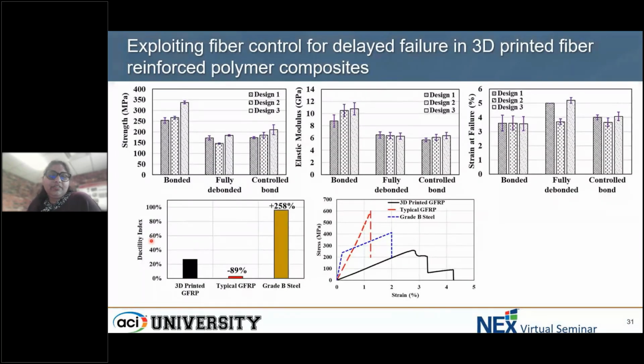Again, strength, modulus, and strain at failures, you will see that the bonded will be at the highest strength in terms of design 1 and design 2. But the design 3, you have a fully debonded one in terms of strain, that is higher strain at failures for fully debonded. And that controlled bond or thermal block also is higher compared to the bonded, which we were trying to achieve. If you look at just comparisons between traditional, unidirectional, typical GFRP composite, it's about negative 89% ductility when compared to a 3D printed GFRP.